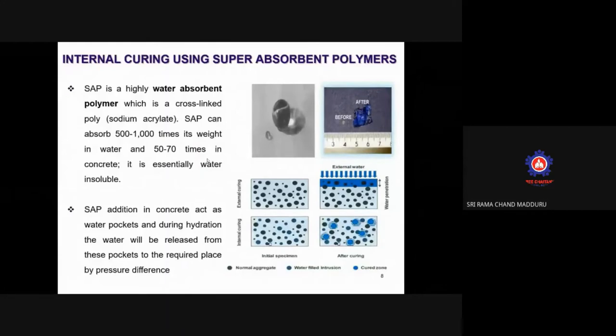And if I go for super absorbent polymers, when they are in contact with water at normal pH, they will increase their volume by 500 to 1000 times. But at a pH of 12 to 13, which is the pH in concrete, they will increase their volume only 50 to 70 times. Before adding these super absorbent polymers in concrete, there is a slight increase in the water cement ratio; the extra water is for the absorption by the super absorbent polymers. The addition of super absorbent polymer in concrete acts as water pockets, and during hydration, the water will be released from these pockets to the required place by pressure difference.